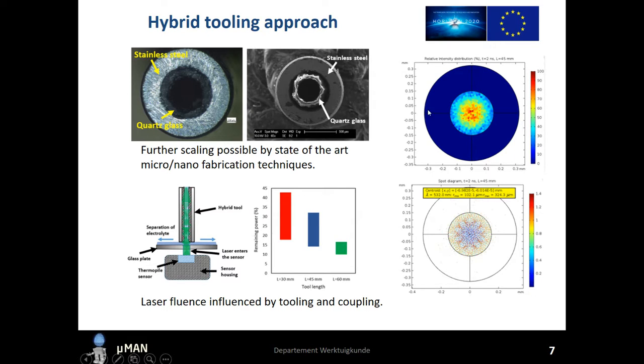On the right-hand side, we can see the simulated intensity distributions at the outside cross section of the tool. The intensity distribution resembles a multi-mode waveguide, where in the center we have higher intensity modes, and on the periphery, close to the internal edge of the glass capillary, we have low intensity modes. It's good to see that most of the intensity distribution is inside the glass capillary, where the electrolyte exists, and there is negligible intensity over the cross section of the glass. On the bottom we can see a spot diagram, which simulates the path of the rays at the cross section on the outlet of the tool. Most of the rays, from the RMS value as well, exit through the internal diameter of the tool electrode, that is, through the electrolyte, and very few exit through the glass capillary.